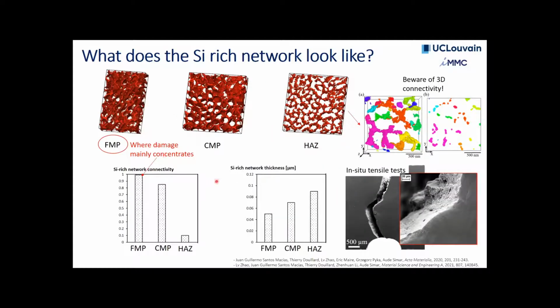Here I'm doing a short quantification of that. So here the fine melt pools. This is the place where mainly damage will concentrate because of the high connectivity that you have. So if you have a highly connected network here, this favors damage in this region.